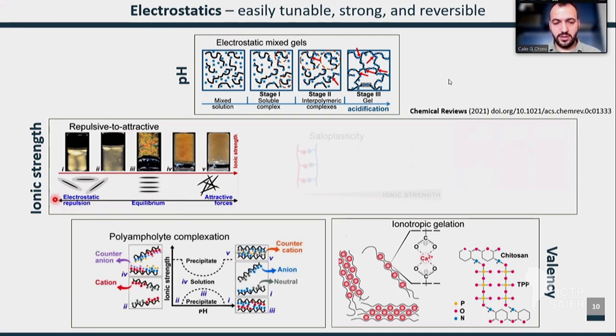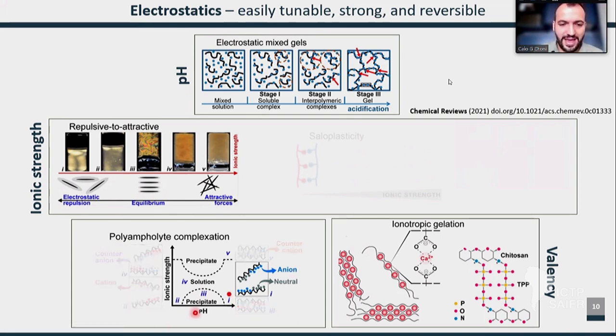So let me dive a little bit into two specific cases. One is polyampholyte complexation that we play a little bit on. So what is a polyampholyte? It's a polymer, actually a block copolymer, and one block is cationic and one block is anionic, so positively and negatively charged respectively. So let's take the first case, when we have a high pH and a low ionic strength. What does it mean? If the pH is higher than the pKa of both blocks, right? So only the anionic blocks are going to be active, deprotonated and charged. The other one is going to be neutral.